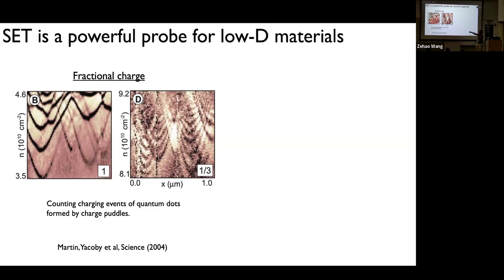Now, if you do the same thing but tune to nu equals 1/3, it's a bit hard to see, but you see that there are many, many more charging lines. These correspond to charging events of electrons or quasi-particles, depending on what the excitation in the system is. Just by counting the number of charging events, if you have a reference, say the integer state, you can immediately say, looking at the right plot and comparing it with the left plot, that the quasi-particle charge is precisely e over 3 with almost no error bar.